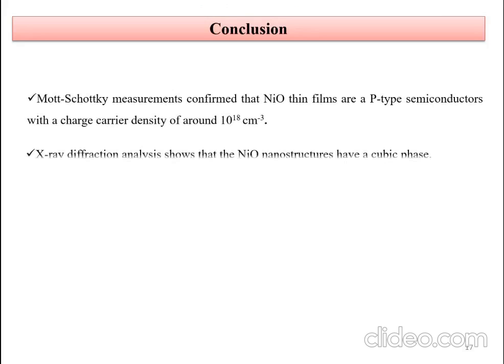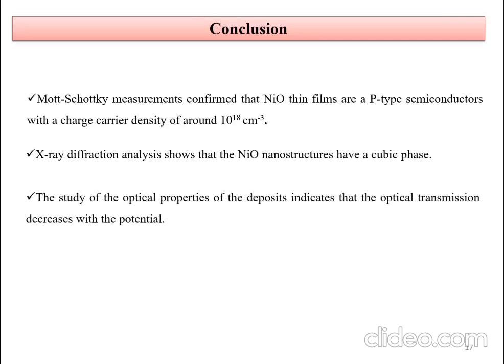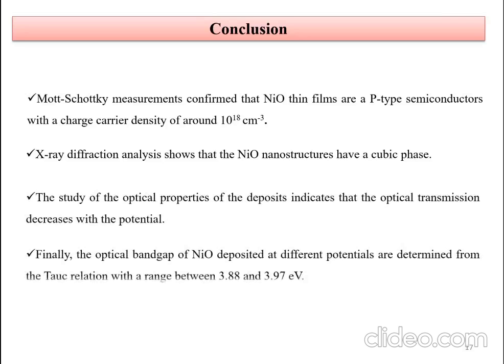As a conclusion, Mott-Schottky measurements confirm that nickel oxide thin films are p-type semiconductors with a charge carrier density of around 10^18 per cubic centimeter. X-ray diffraction analysis shows that the nickel oxide nanostructure has a cubic phase. The study of the optical properties of the deposits indicates that the optical transmission decreases with the potential.